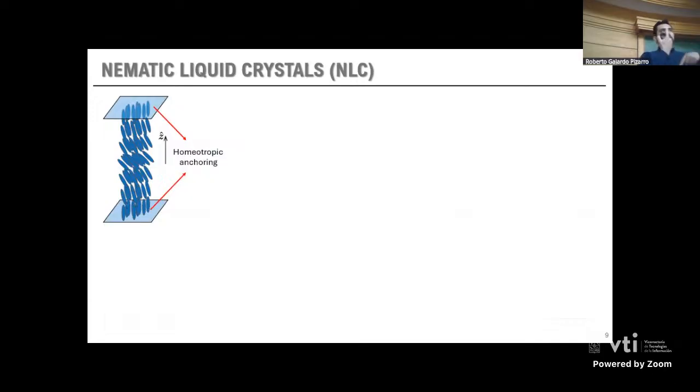to make the molecules align perpendicular to the glass plates, the elastic stresses are going to generate an orientation roughly perpendicular to the nematic liquid crystal plane. So, in this case, if we apply an external, for example, electric field, and if the dielectric anisotropy of the material is negative, the molecules will want to align perpendicular to this external electric field. But we also have the elastic stress coming from the material, so we have this competition between these two effects.